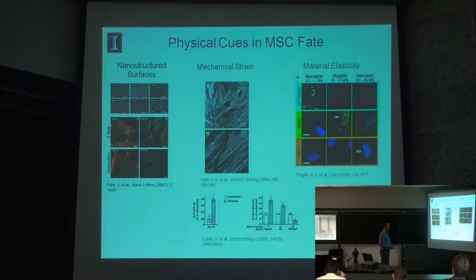A real seminal work came out of Dennis Discher's lab at Penn with Adam Engler as the first author, who's now at University of California, San Diego, and visited us last year, I think. Adam and Dennis published this paper in 2006 that I think really changed the way a lot of the material scientists in bioengineering thought about these things. What they did is they did a simple experiment by varying the stiffness of polyacrylamide gels, so standard gels used for running protein gels, from very soft gels that approximated the stiffness of brain tissue, so less than 1 kilopascal. And then they increased the cross-linking density of those gels to make them more rigid, to approximate that of muscle tissue and bone tissue.